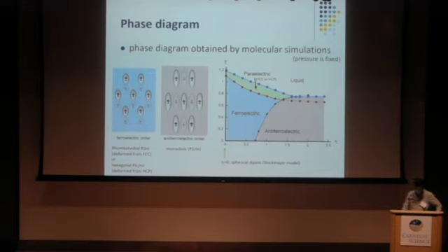The crystalline phase is slightly deformed from the mother FCC or HCP phase. But for very large anisotropy, in the right part, a completely different phase emerges, the antiferroelectric phase. This is schematically written in the middle one, where the dipole moments align in an anti-parallel manner to adjacent particles to decrease the electrostatic energy. So the crystalline phase is completely different. Okay, I will explain later.